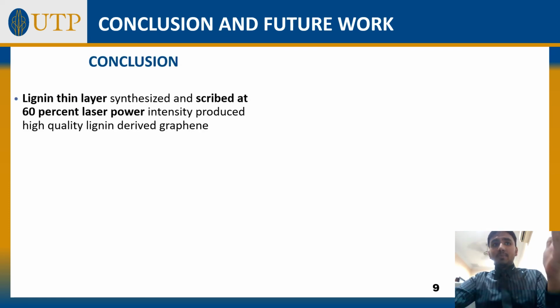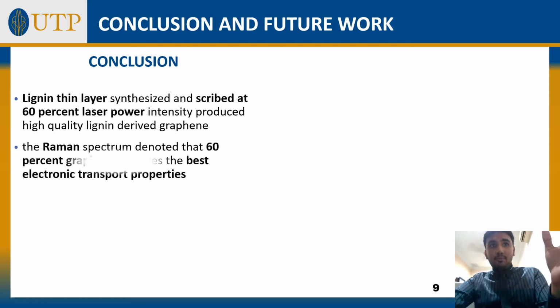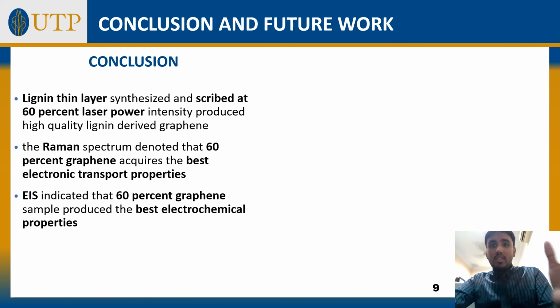To conclude my presentation, I would like to say that lignin thin layer was successfully synthesized and scribed, and the best laser parameter was 60% laser power to produce high quality lignin graphene. This was proved by the Raman spectrum, showing that 60% graphene had the best electron transport properties, and the EIS spectrum also showed that 60% graphene has the best electrochemical properties.